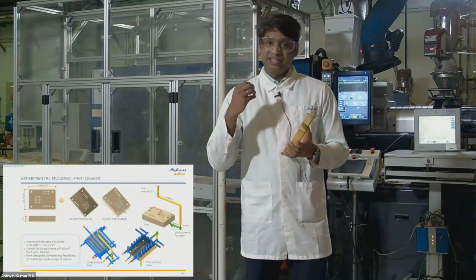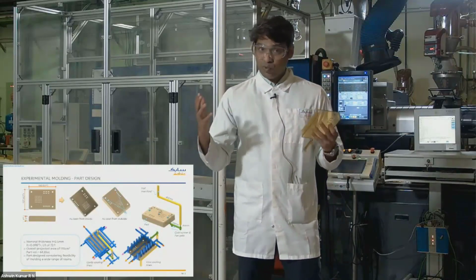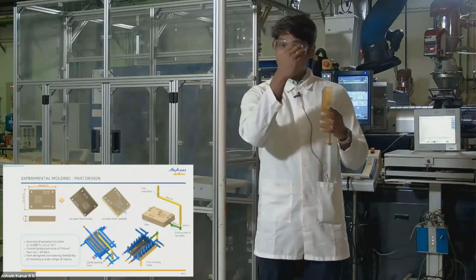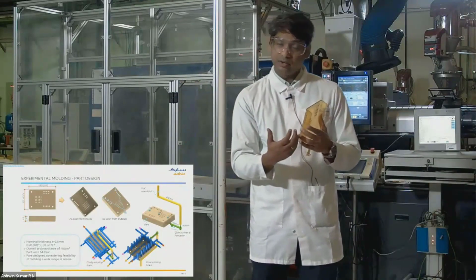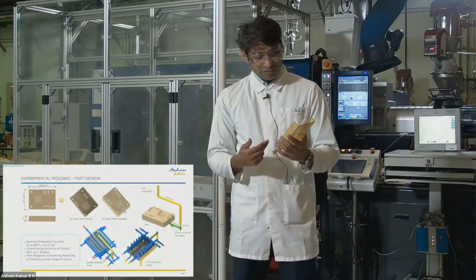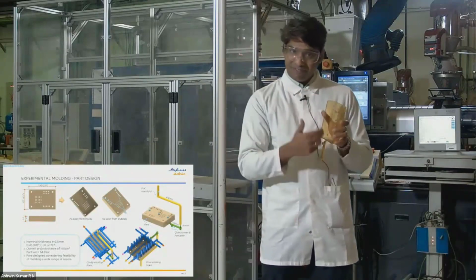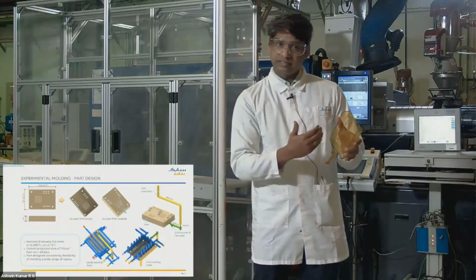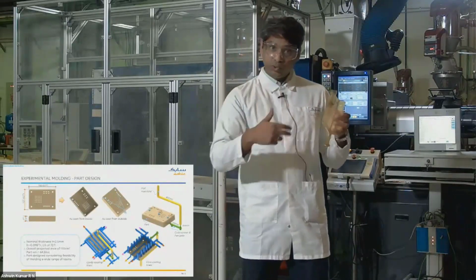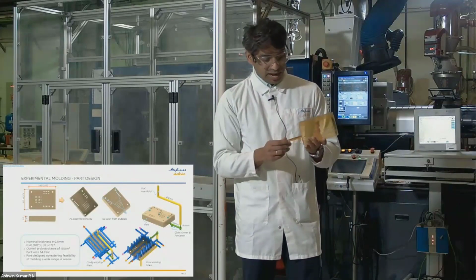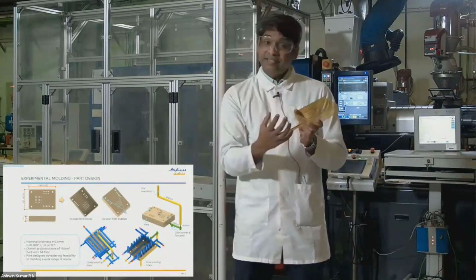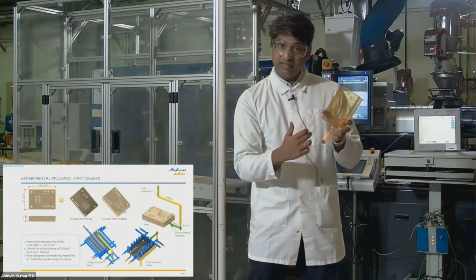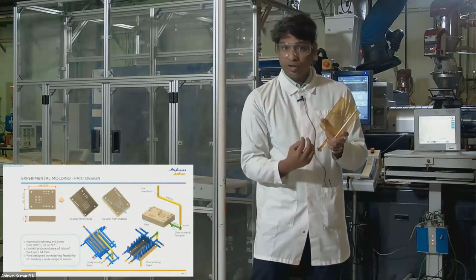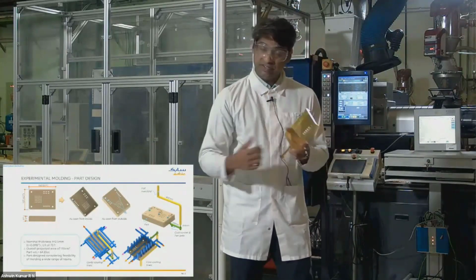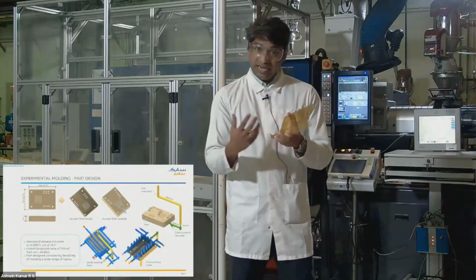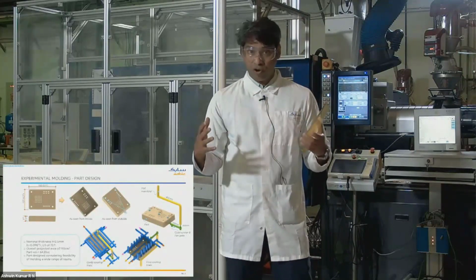So for that, we engineered the cooling channels in such a way that the temperature variation between the two halves of the mold and also even on the same side of the mold is less than 1 degree between them, right? So for that, you can just look at the screen, the small screenshot there. There are baffle coolings within the core, and surrounding the core is another cooling channel. And on the cavity side, there are additional 2 cooling channels which are trying to maintain this temperature altogether. And another important thing I want to highlight here is maintaining the temperature at the hot runner. So we have a separate cooling channel designed in the tool to maintain the steel close to the hot runner at a nominal temperature, and we connected it to a separate MTC, which I'm going to show you in some time. This is really helping us to make sure that the temperature distribution is uniform in all of the mold.